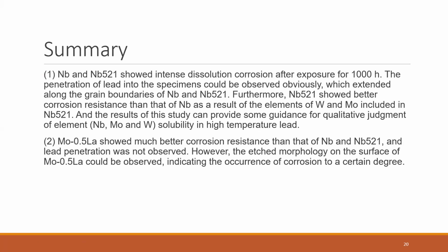So, summary from this paper. One, niobium and niobium alloy showed obvious dissolution corrosion after exposure for 1000 hours. The penetration of lead into the specimen could be observed obviously, extending along the grain boundaries of niobium and niobium alloy. Furthermore, niobium alloy showed better corrosion resistance than niobium as a result of the tungsten and molybdenum included in the niobium alloy, and the result of this study can provide some guidance for qualitative judgment of niobium, molybdenum, and tungsten solubility in higher temperature lead.